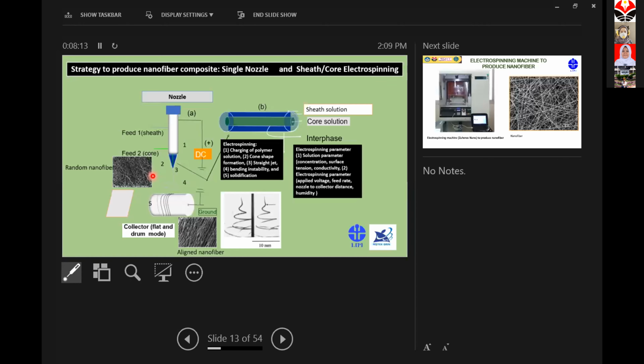The principle of electrospinning to make nanofiber is very simple. We use a DC electrical current, high voltage. This mechanism follows charging of polymer solution, cone formation, jet formation, bending instability, and solidification of the polymer jet.